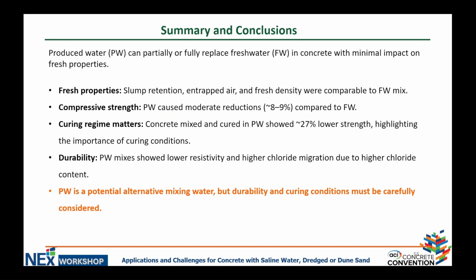So to summarize and conclude what I said, we have used produced water for making some concrete mixes, and we did lots of different fresh properties and basic mechanical properties testing. What we can say is that fresh properties are not affected by produced water. For mechanical properties, when the only variable is the type of water, the decrease in compressive strength is not really that bad. It's 8 to 9%, which is generally accepted in the concrete industry. But again, curing seems to have a very big role, and that's part of the future work that I'm going to talk about in the next slide.